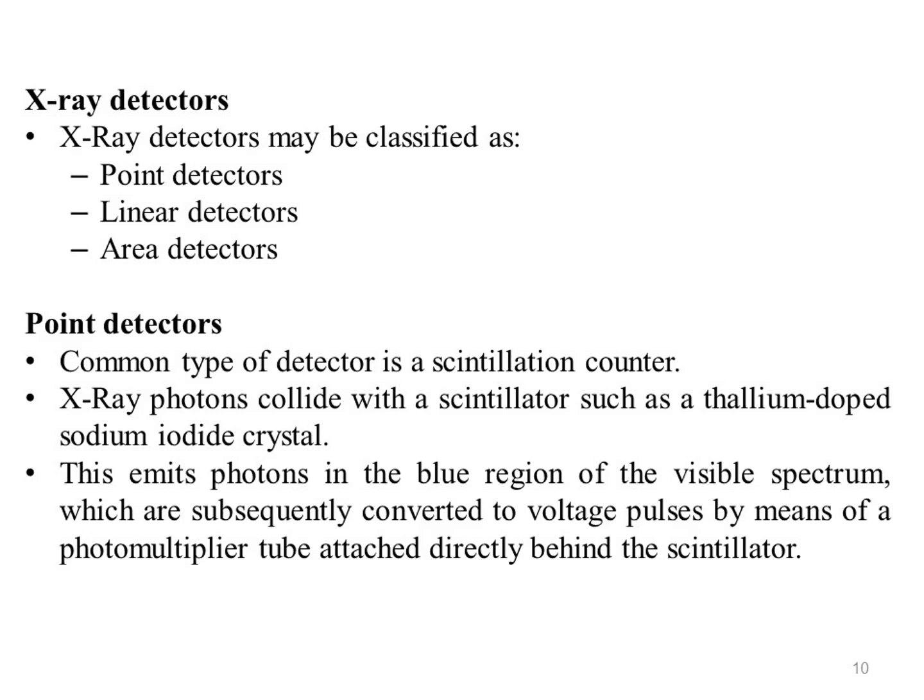Point detectors are easily compatible with post-sample optical elements. Linear and area detectors allow the data to be acquired much faster, but as more open systems, they are prone to detecting parasitic scatter from the air or sample environment. Both linear and area detectors are types of position sensitive detector, abbreviated as PSD.